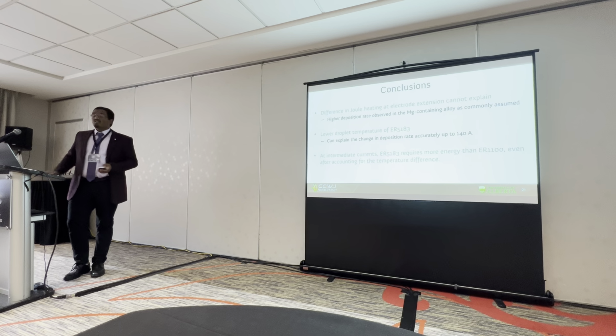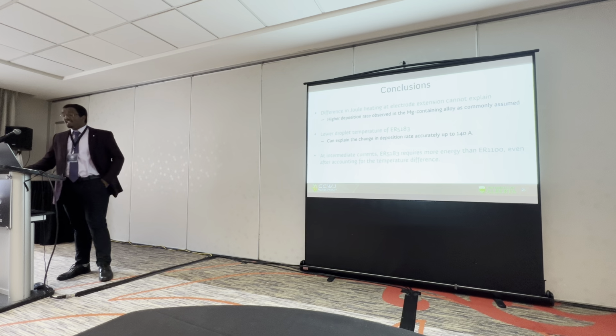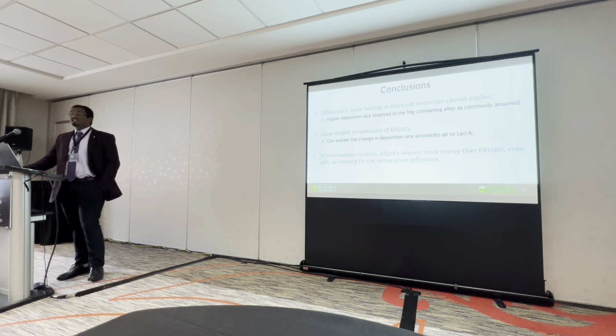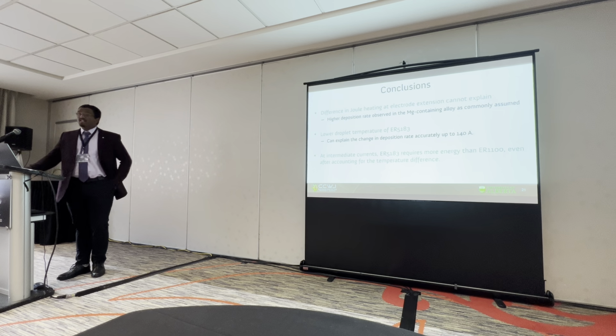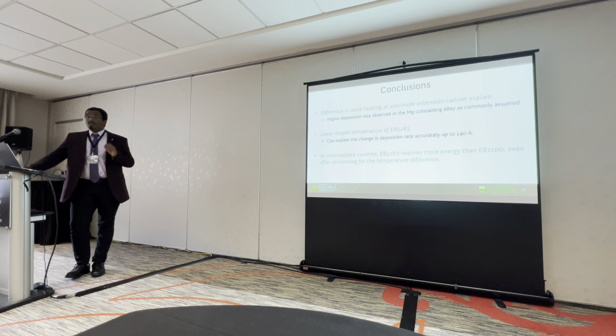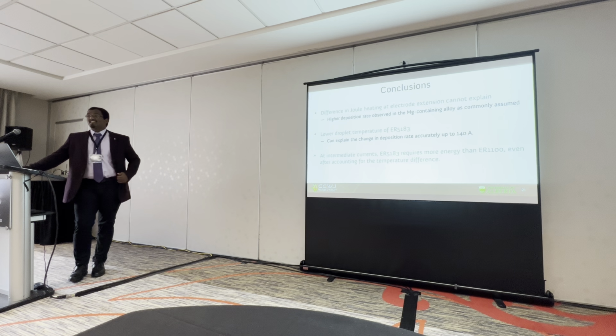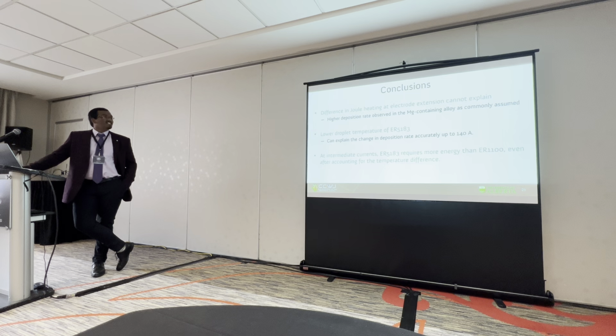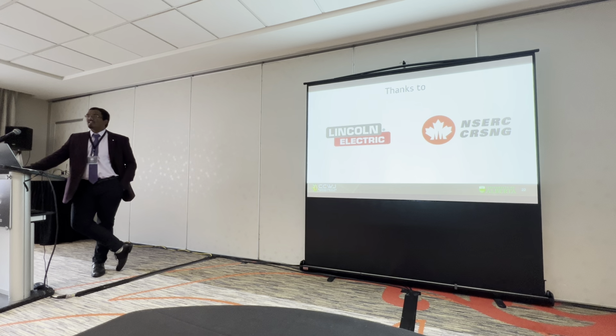So, to conclude, the difference in Joule heating and electrode extension cannot explain the reason behind the higher wire feed speed we have in magnesium containing aluminum alloys. But the lower droplet temperature can explain the higher wire feed speed below 140 amperes. At intermediate currents, we still need more. We still need to understand why we have this higher thermal energy. That is the part which is yet to be discussed and researched further. So thanks to Lincoln Electric and NSERC for funding.